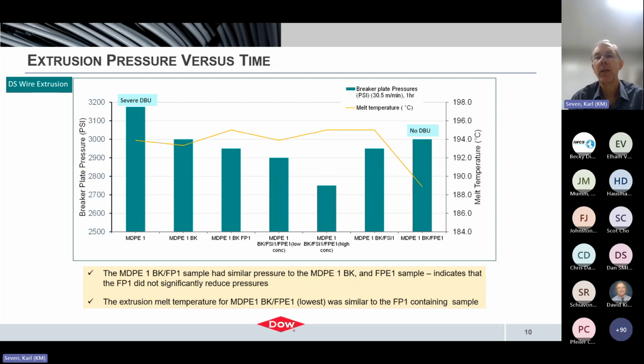Extrusion melt temperatures for the polar polymer additive sample were similar to the fluoropolymer-containing samples. These results pretty much indicate that processing should be similar with the polar polymer additive sample versus the comparative with the typical PFAS-based processing aid.